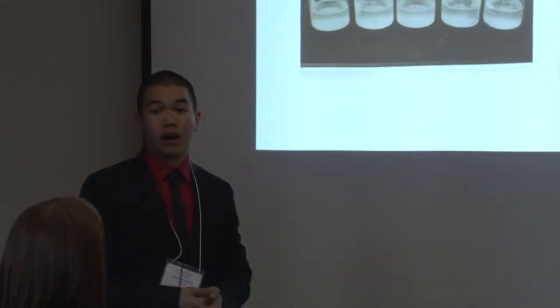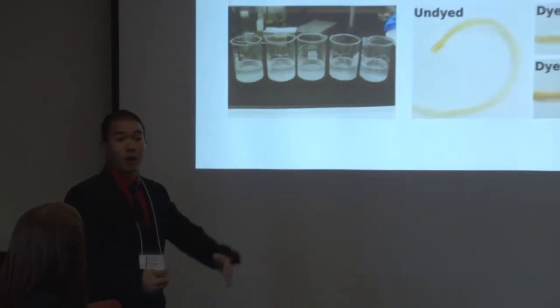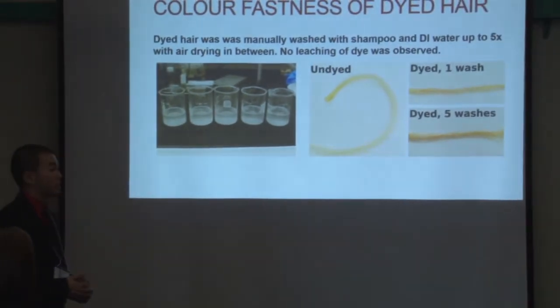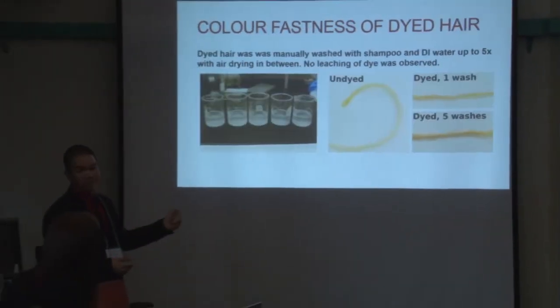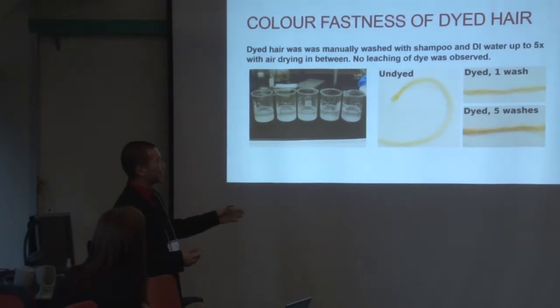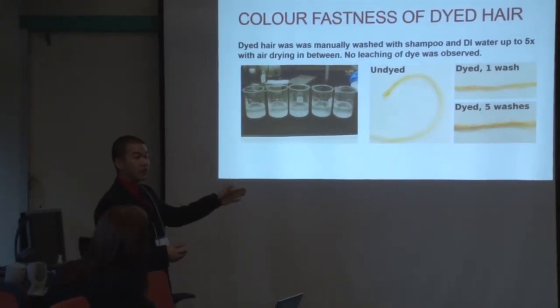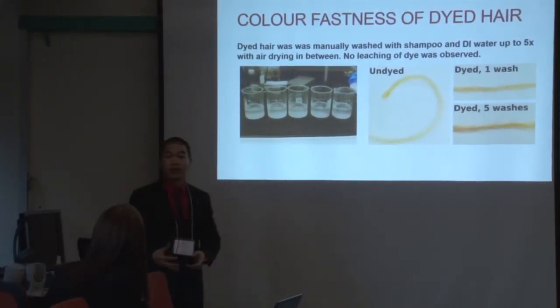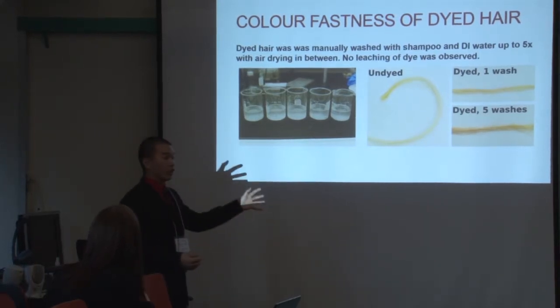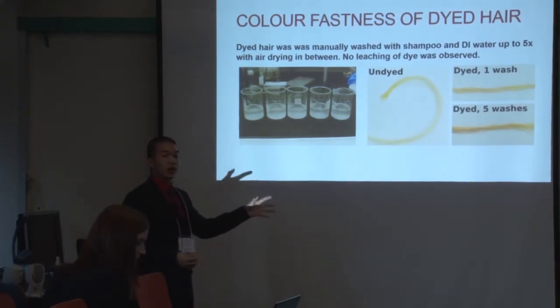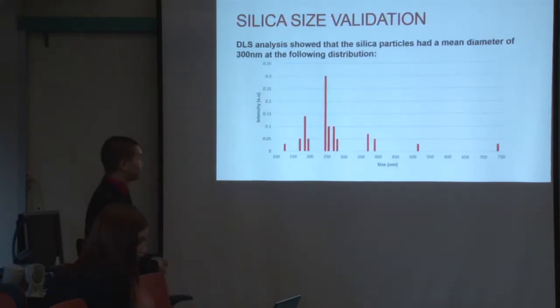And the result was, after 5 washes, we found that there was no observable leaching of the color or color change. We actually wanted to wash the hair until the hair color came off, but unfortunately we did not have enough time. Because 5 washes is in the range of current semi-permanent dyes, we think that as a proof of concept, this is enough to show that our dye can compete with existing products on the market.